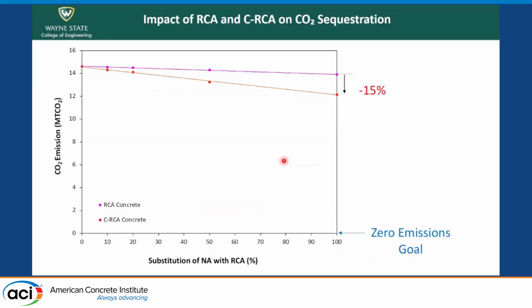In this slide, I'm showing you a projection of the CO2 emissions reduction with the different percentages of substitution of natural aggregates with recycled concrete aggregates. And we only observed a 15% decrease in CO2 emissions when our substitution was at 100%. That means we do have a lot of room to improve. And this is where we thought about using an additional material inside the new cementitious matrix, the new mortar, to achieve an additional CO2 uptake.